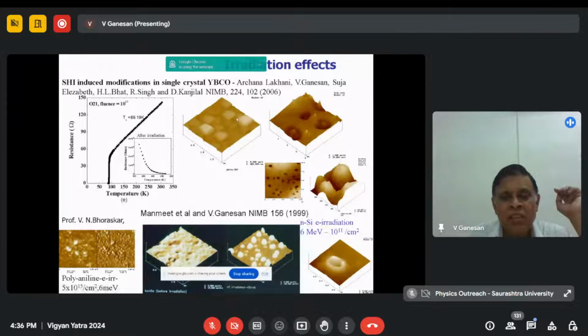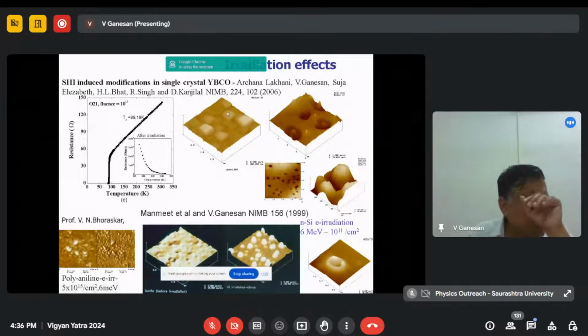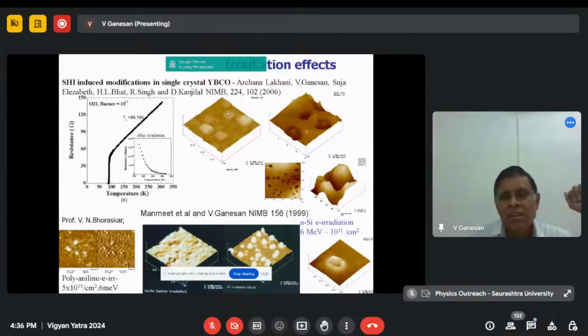The grain boundaries are devoid of oxygen, therefore they become insulators compared to the grains. So insulators preserve the heat for a longer time. Therefore, the amount of thermal spikes is easy to understand, and they specifically erode. Therefore, you can see there is always a center, and the surrounding portions are getting easily eroded by this. Same thing here is very clear. One grain to another grain, the portions in between are all eroded.